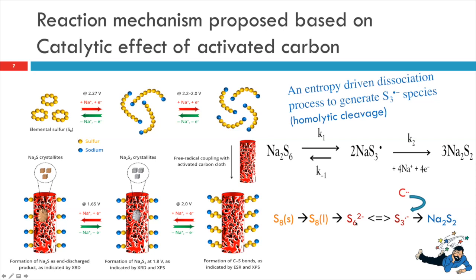And what we are proposing is that we are identifying this S3 monoanion being produced. Also, due to this, a highly corrosive surface was produced, where a dangling bond was produced, which acts as a free radical again. So here what we are proposing is, once it is formed, it immediately couples with the radical from the carbon,